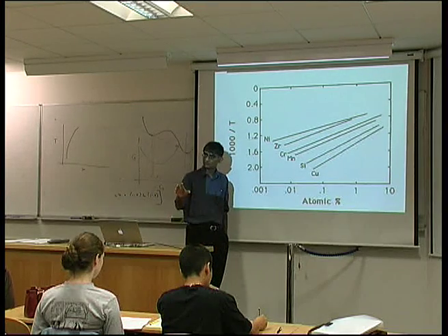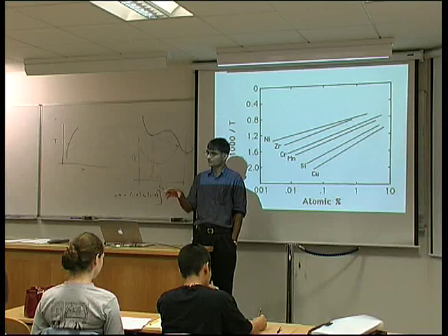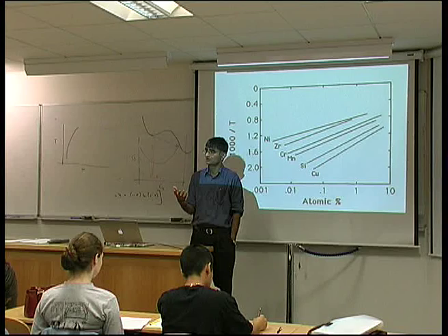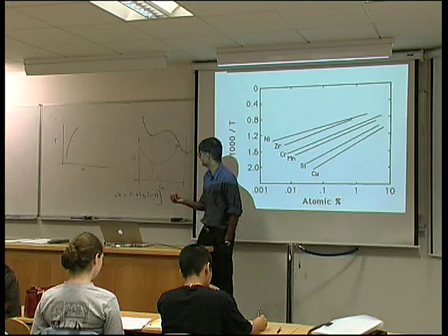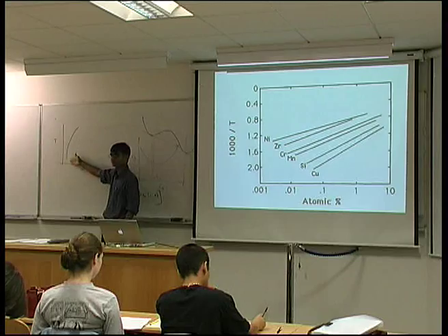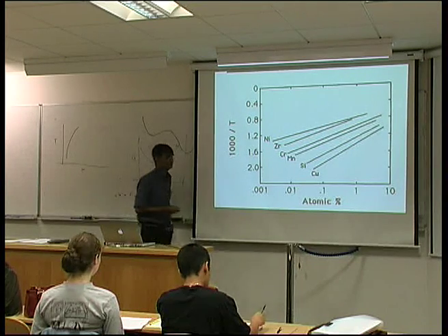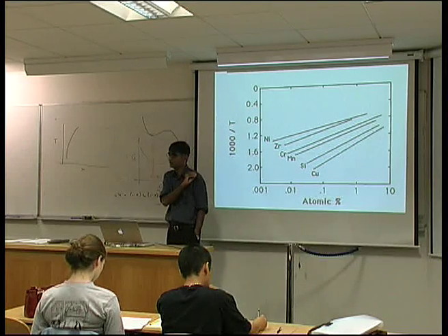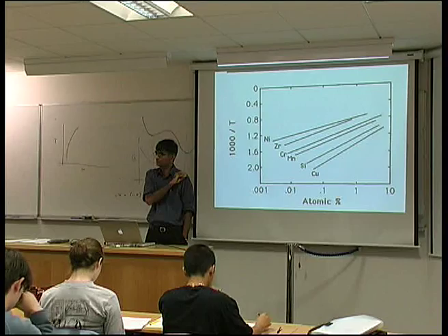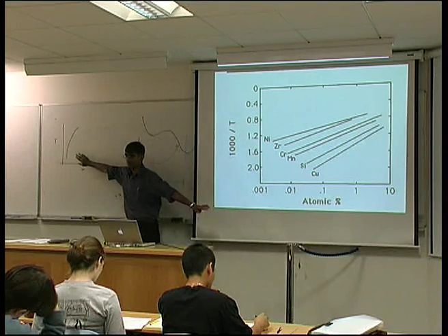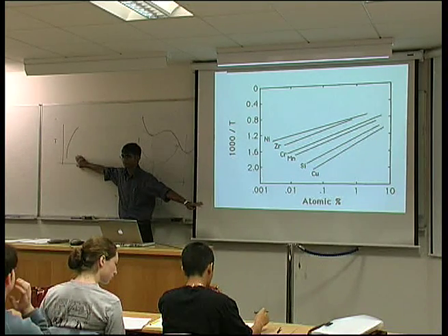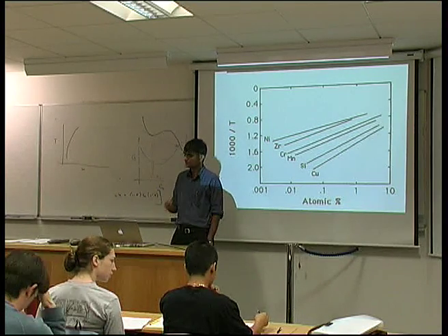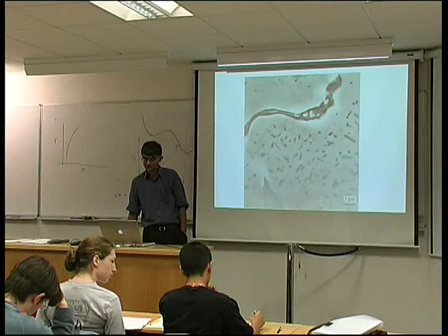So what we've done is, we've used the elementary thermodynamic theory that you've done previously for solutions, and from that we've derived an equation for the solubility of solute in aluminium. And if you have knowledge of one single parameter, omega, then you're able to calculate these solubility lines as a function of temperature. So these lines are exactly this, it's simply plotted differently. So you can find tabulations of omega, and therefore you can design your heat treatment project. Now,